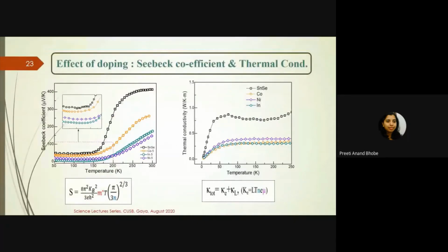But if we see, the Seebeck coefficient is also drastically affected. The Seebeck coefficient goes really low with doping of other elements in place of Sn in the compound. Interestingly, even the thermal conductivity is reduced. This is a good result, because if the ZT has to go up, the thermal conductivity in the denominator has to come down. And with these dopings, thermal conductivity is reduced to 50% of what is found in SnSe.